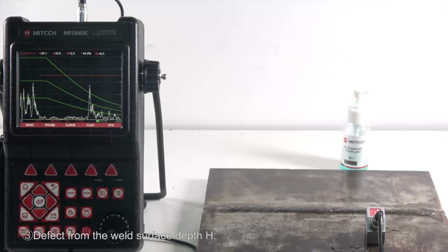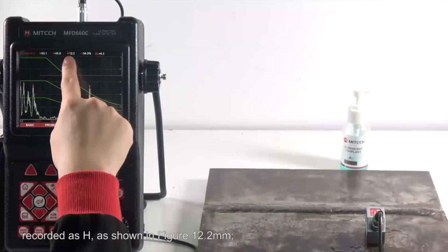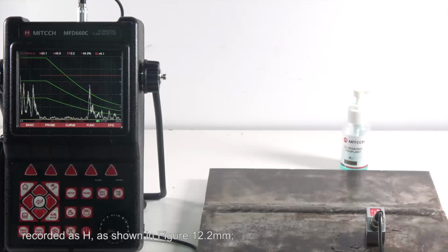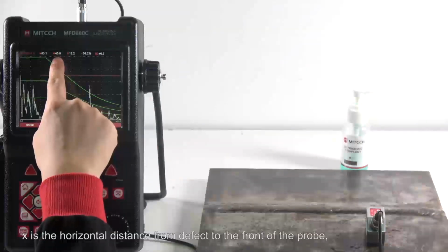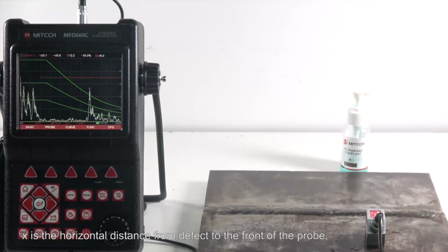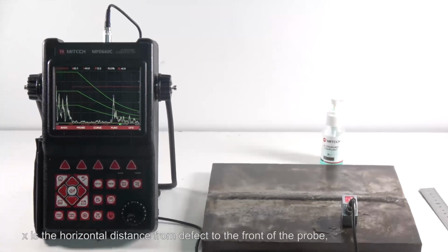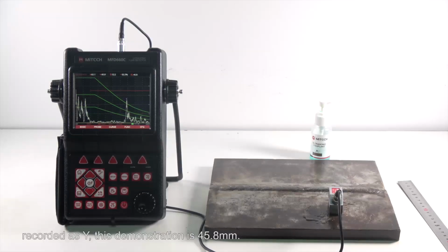Defect depth from the weld surface, H. Read the depth of the defect, reading X millimeters, and record it as H. As shown in the figure, it is 12.2 mm. Defect distance from the center of the weld, Y. Read the horizontal reading X millimeters, which is the horizontal distance from the defect to the front of the probe. Recorded as Y, this demonstration is 45.8 mm.